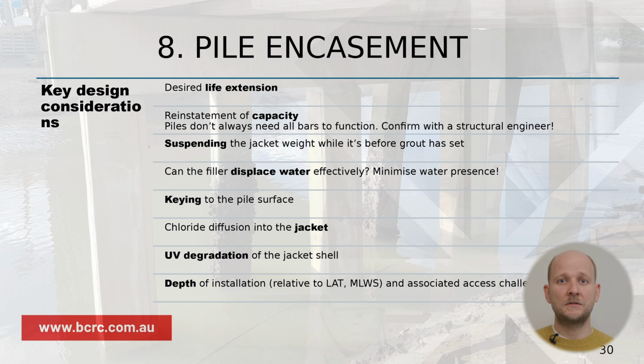The other aspect of design to consider is chloride diffusion, especially if you're dealing with additional steel reinforcing inside the jacket, because your existing pile concrete would contain some chlorides, and as soon as the repairs are done, these chlorides will diffuse back into the jacket, into the cementitious material, and this might cause very early corrosion if you're not providing sufficient cover or not addressing it otherwise, like installing stainless steel inside the jackets.